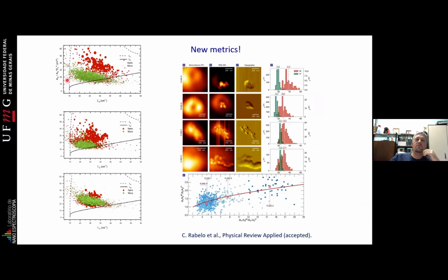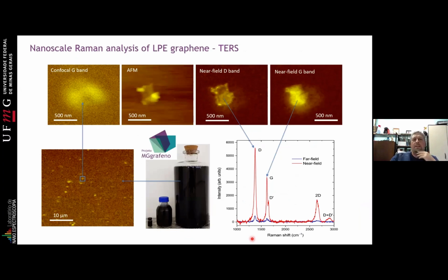We measure the amount of defects, and there are a lot of new metrics involved here. If you're interested, you can read this paper. But here's the thing: if you want to analyze just one flake by Raman, it's blurred like this, because we don't have spatial resolution. But with AFM, we see the flake. The flake has a lot of structures. It may have some chemistry attached. It's not just a single, nice, uniform flake.